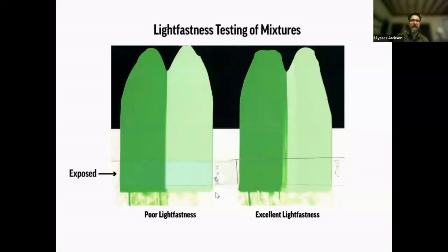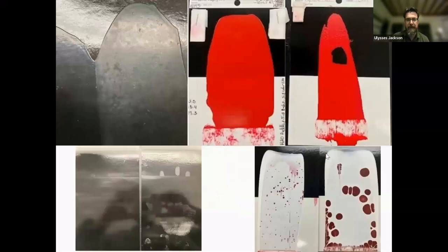And so we have exposure chambers. Xenon arc is one we use a lot, and this image is from a xenon arc chamber, where it's like an easy bake oven on steroids. I have 2 greens here, and these greens are mixed with the same amount of white paint. And then this bottom portion, this little snip, was exposed. You can see this one on the right side had very little change in the equivalent of 100 years of museum lit condition. And this one had dramatic loss of yellow. So in our directions, we would of course not pursue that yellow. We would pursue the more stable yellow, which in this case is benzimidazolone yellow light, that PY175 shown earlier.